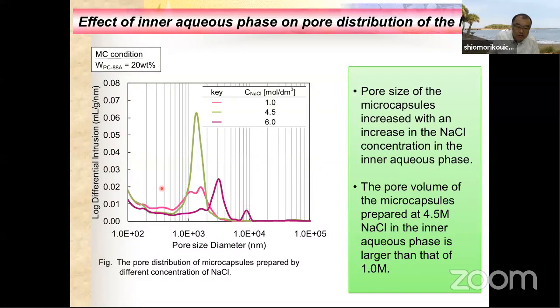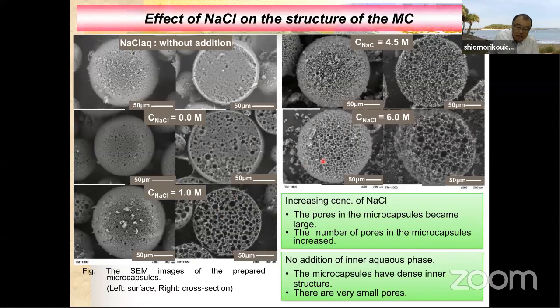This slide shows the pore diameter distribution when we change the concentration of sodium chloride in the inner aqueous phase. When we use a high concentration of sodium chloride, the pore diameter moved to a larger area here. So we can control the pore diameter by changing the concentration of sodium chloride in the inner aqueous phase.